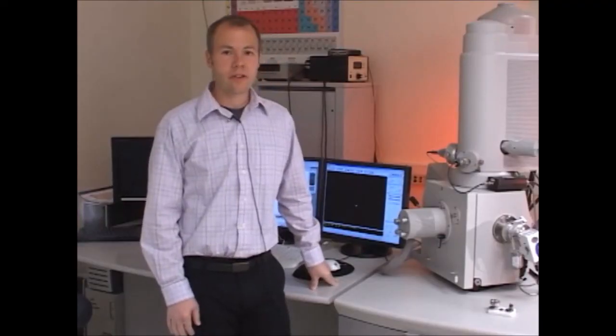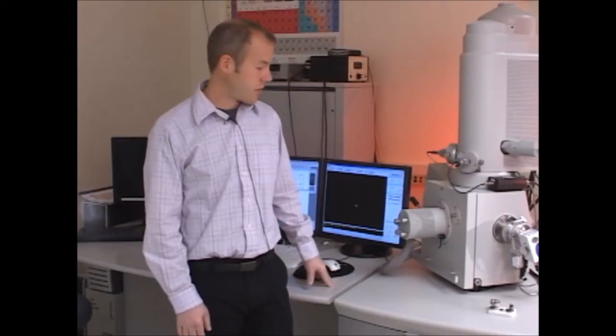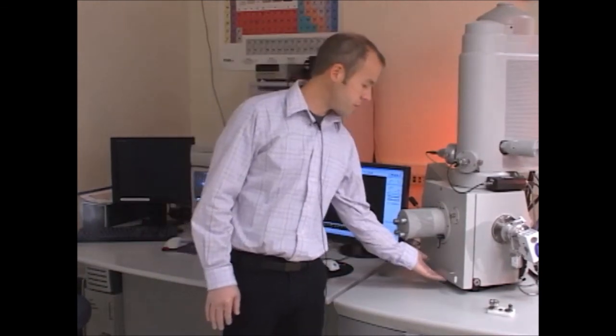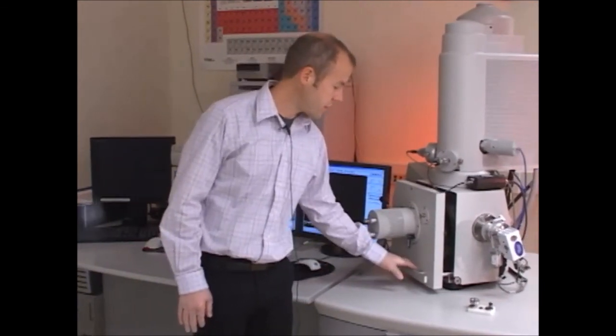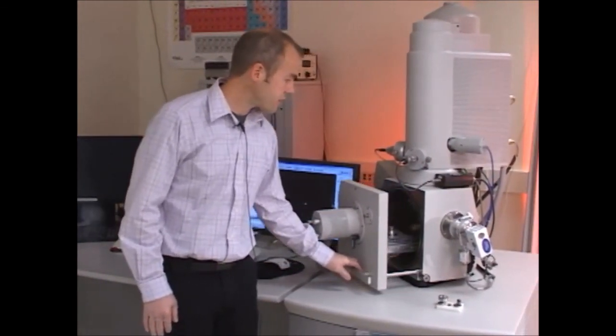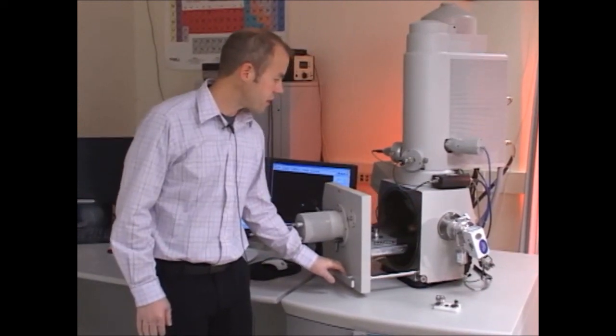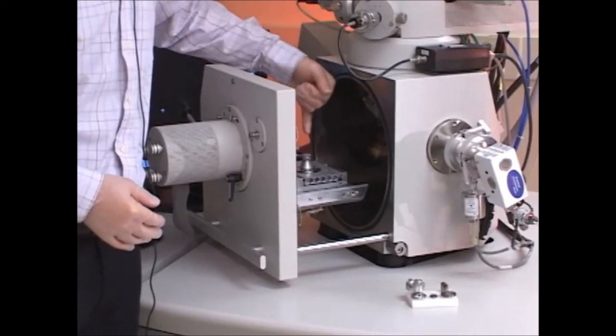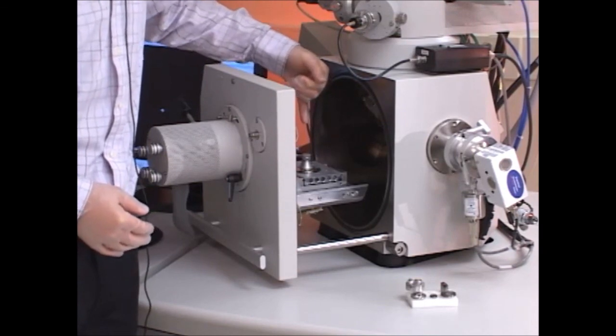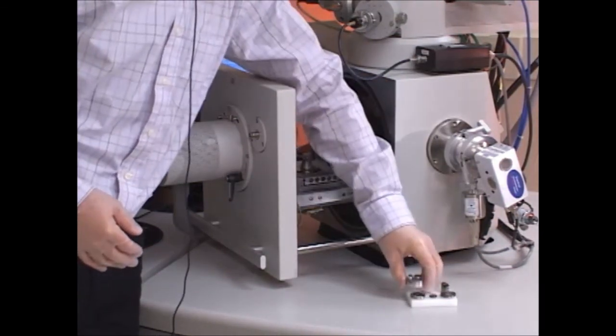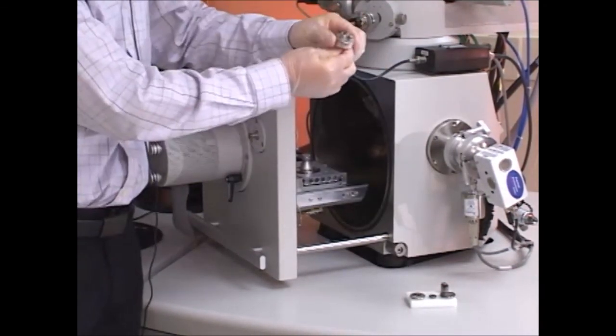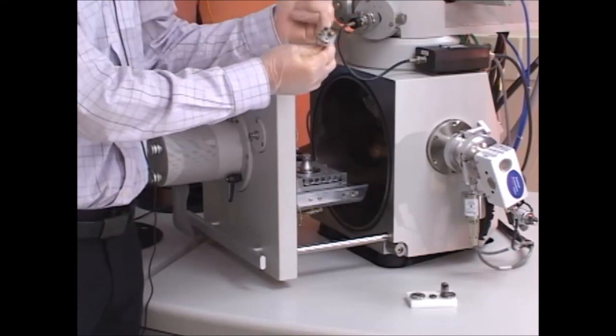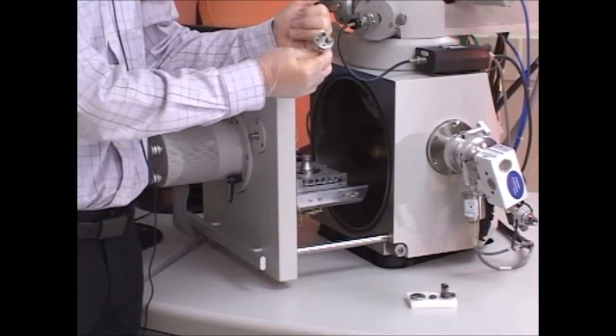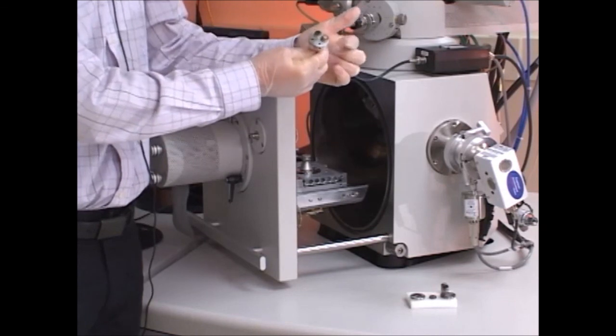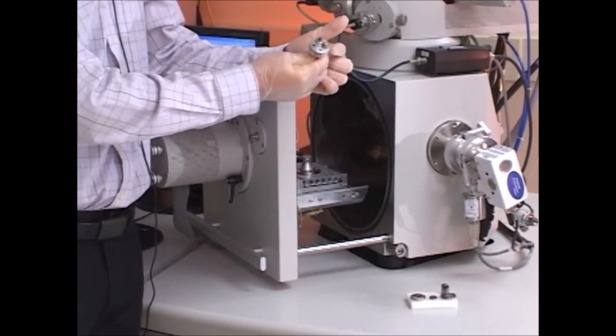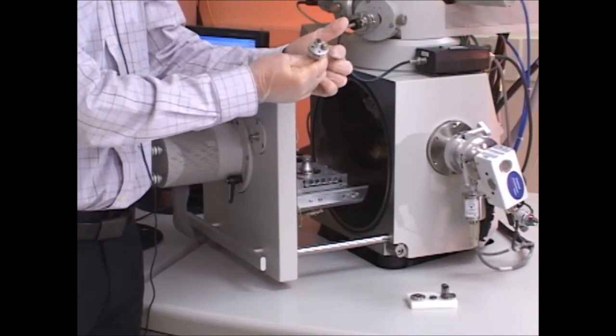So we've waited long enough for the pressure to equalize in the chamber, and I'm just going to open the door again by pulling on this handle and open it gently until it reaches the stop position. So you can see there's just one position in the stage chamber here for the pin mount sample. I'm going to take the sample that I mounted earlier with the gold nanoparticles on carbon at the top, the 12 o'clock position, and then at the 3 o'clock position is the yellow tin sphere sample.